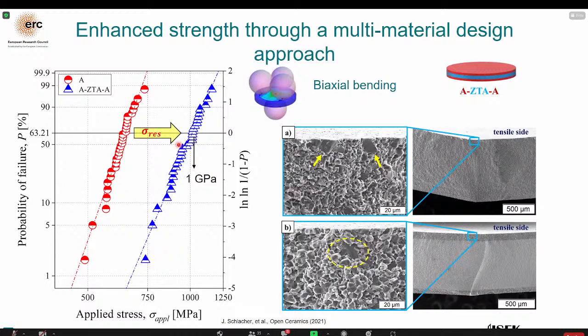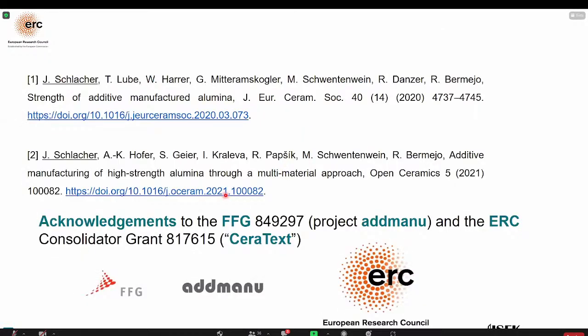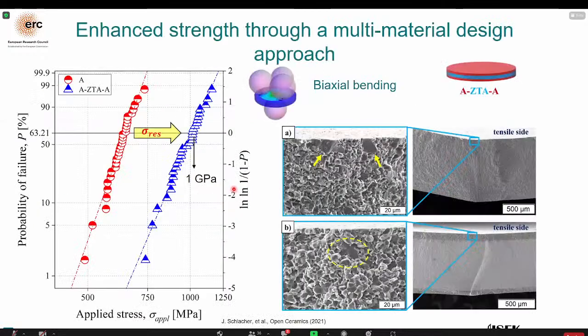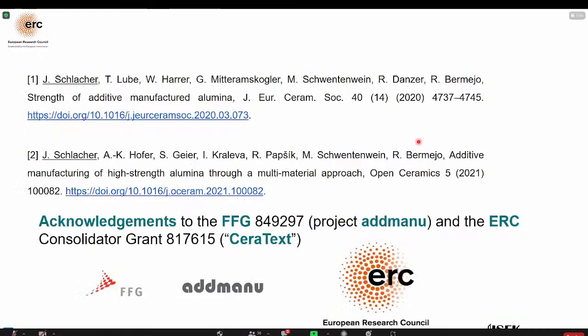I need to note that the samples were tested in biaxial loading, which means the ball-on-three-ball test was used. On the fracture surfaces, we can see that fracture in the laminate structure always originates in the alumina outer region and not at the interfaces or at the middle layer. So thank you for your attention.